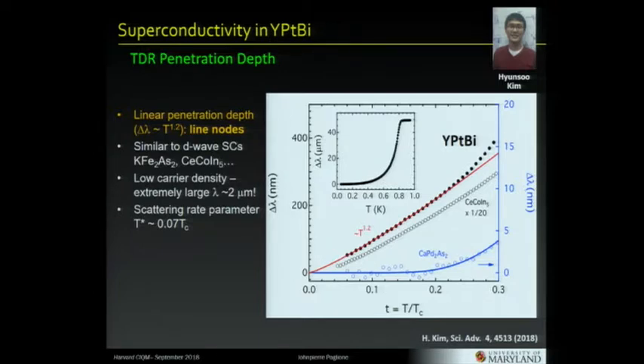So here's the data. Yttrium platinum-bismuth is in black, and then just to compare to some other classic superconductors, this is a classic BCS S-wave fully gapped superconductor. In this range of fraction of TC temperature, this is just nothing. This is just an activated penetration depth that slowly rises as you go towards TC. In this classic D-wave superconductor, there's a nearly linear rise in the penetration depth. It's a signature of a nodal superconductor with nodes in the order parameter in K-space. In yttrium platinum-bismuth, we find that this is nearly linear as well. And then just note the scale. The scale here, which is absolute for this one, is divided by 20 for this. That just tells you exactly right there that the penetration depth scales with this inverse of carrier density very well. So it's a very nice big signal that we can measure very easily. So it's a perfect experiment for this system.